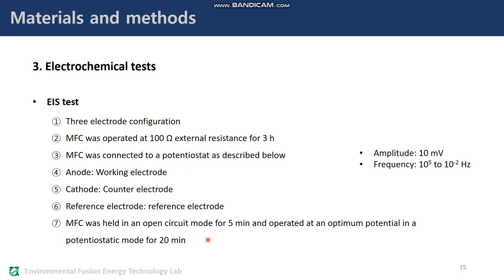MFC was held in an open circuit mode for 5 minutes, and operated at an optimum potential in a potentiostatic mode for 20 minutes. Anode impedance was measured at an optimum potential for each anode, where maximum power is produced. 10 mV of the amplitude of the alternating voltage of the frequency range were used for anodic impedance measurement.